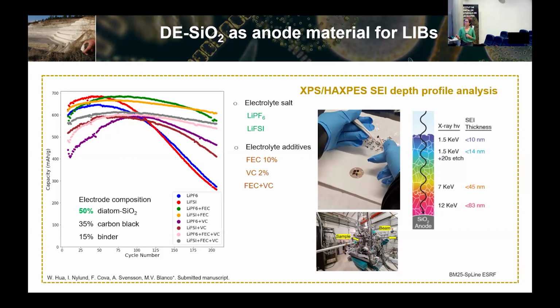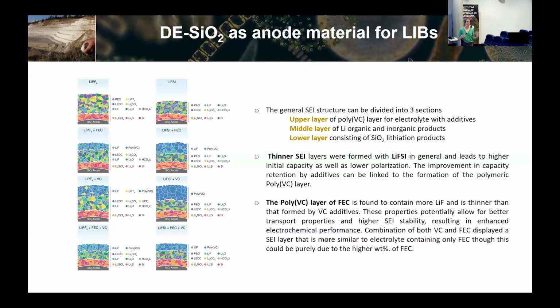So I won't go too much into this, but we were actually able to build some model where we could divide the SEI into 3 different regions. An upper layer would have this poly VC, the middle layer would have more organic and inorganic components, and then the lower layer was where we saw more of the silica lithiation and delithiation, which means that we were able to go through the whole SEI, which is nice, because if you are able to go through all of it, then it means that you can have an idea of how deep it is. Okay, I won't go too much into this, but just to say that there are ways to improve a bit the capacity of the material, even though the material is not super great.